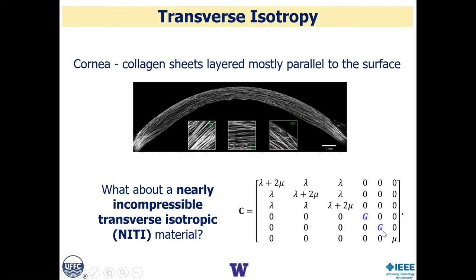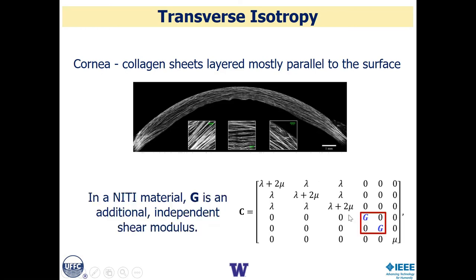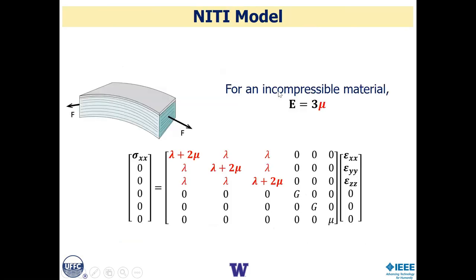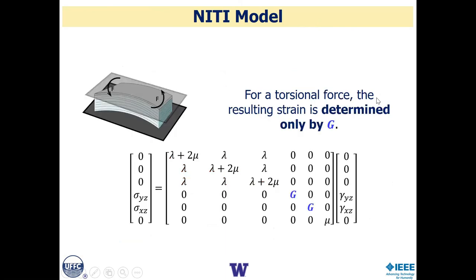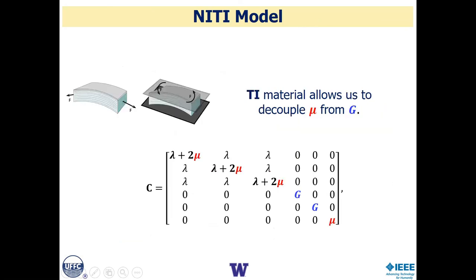So the simple mechanical stiffness matrix for an isotropic material must change now to one in which we have 2 shear moduli. But we don't change the longitudinal terms because this is for a nearly incompressible material. So we focus on these two. The reason is because for an incompressible material, the mu simply determines the Young's modulus and has this fixed constant of 3. But the in-plane shearing characteristics are now determined by G. So we thought we have decoupled mu from G.